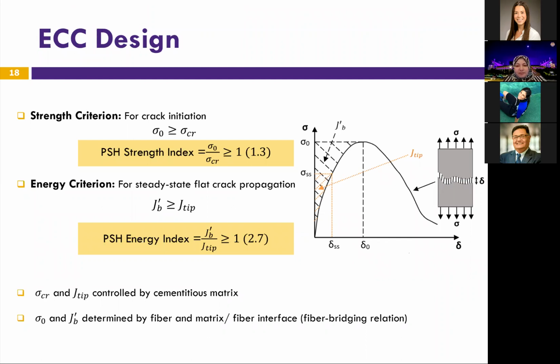So how do we design ECC? There are two basic criteria that must be met for successful design of ECC materials, what we call the strength criteria and the energy criteria. The strength criteria warrants adequate fiber bridging capacity upon crack initiation, whereas the energy criteria guarantees the occurrence of steady state crack propagation. The strength criteria require that the maximum fiber bridging capacity, sigma naught right here, is larger than or equal to the matrix cracking strength, which is sigma critical. The energy criteria require that the complementary energy of the fiber bridging relation, which is JB right here, is greater than or equal to the crack tip matrix toughness, J tip over here.